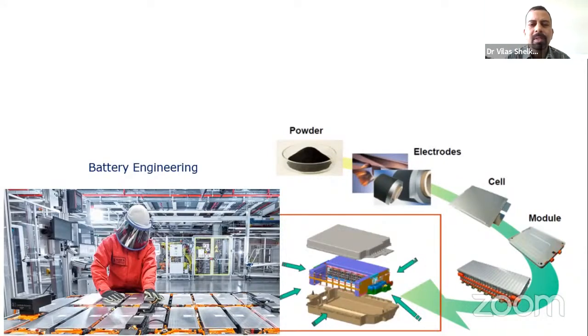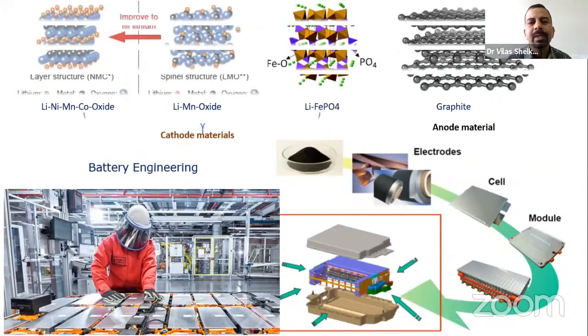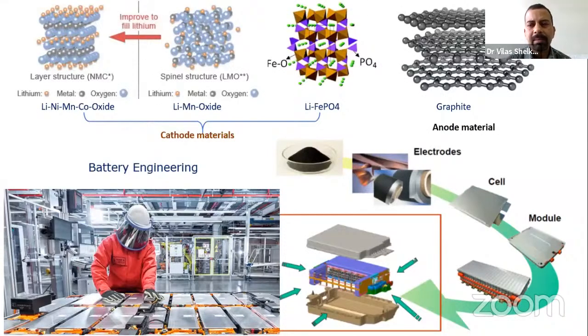That is the part where most of the parameters or properties of a battery are governed or defined. So the most common choice for commercial battery anode is a graphite material. You know that graphite has a layered structure, so there is a space between these different layers, and the lithium ions, being a small ion, can comfortably sit in between these different graphite layers. So a large number of lithium ions can be accommodated inside the graphite layers, and that is how graphite has a very high energy density or energy capacity, because there is enough room for more lithium ions.